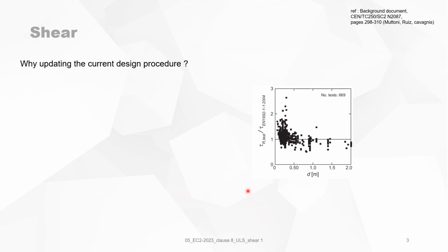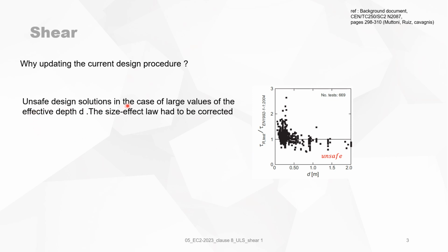And from the different data, for instance, 669 tests, if you group them together into a graph with the x-axis, the effective depth d, and on the y-axis, the ratio of the resistant shear force from the test divided by the one predicted by the present Eurocode version 2004. When you look at this graph, you will see everything which is smaller than 1 is unsafe. So you see immediately there are quite unsafe results in the tests that were carried out. So unsafe design solutions in the case of large values of the effective depth d, and the size effect law had to be corrected. And when d gets bigger, you will see there is none of those test results in this region. So this was not okay.